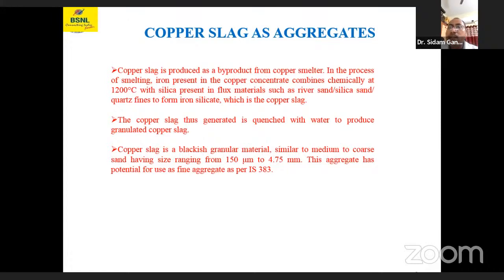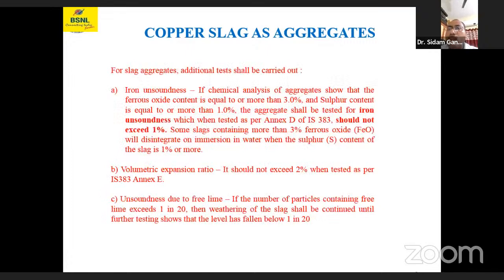Also, copper slag is a blackish granular material similar to medium to coarse sand, having size ranging from 150 micrometers to 4.75 millimeters. This aggregate has potential for use as an aggregate as per the IS 383 codal provisions. Here, the volumetric expansion ratio should not exceed 2% when tested as per IS 383.